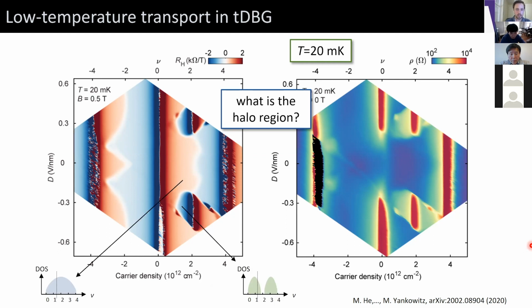So the main question right now is, what is this halo region really telling us? And to get a basic idea, we can consider what is the consequence of actually opening a gap at half filling of the band. The consequence is that we have to break some symmetry in the system. The band is initially fourfold degenerate and spans filling factors 0 to 4. And it has 2 spin and 2 valley degrees of freedom. And if we're to see an insulating state at half filling of this band, that means that we have to break spontaneously one of these symmetries and open a gap.